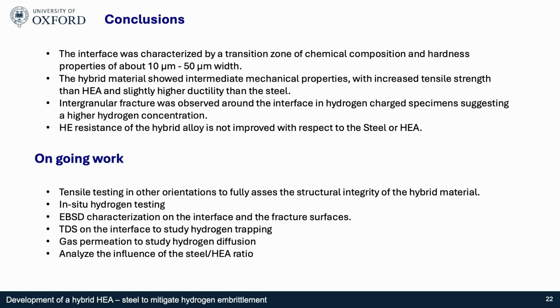So as a conclusion, we can say that the interface is a transition zone in terms of chemical composition and hardness of about 10 to 50 microns. Then the hybrid material shows intermediate mechanical properties with a higher tensile strength and a little bit higher ductility than the steel. And the intergranular fracture observed around the interface in the hydrogen-charged specimens suggests that there is a higher hydrogen concentration there, and that the hydrogen embrittlement resistance of the hybrid alloy, once charged with hydrogen, is not improved with respect to the steel or the high entropy alloy.